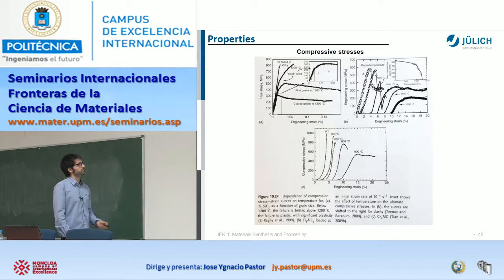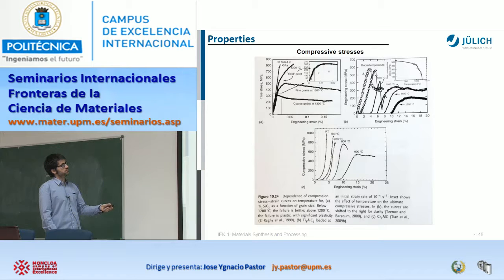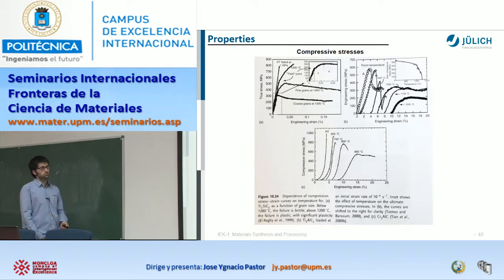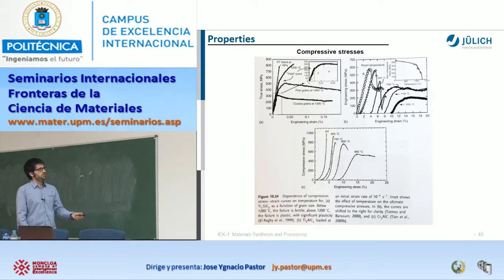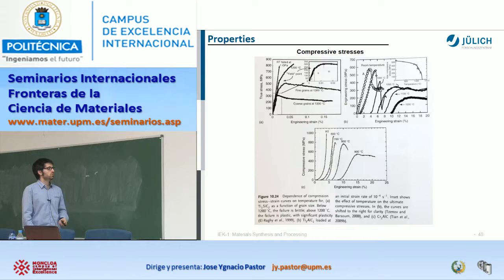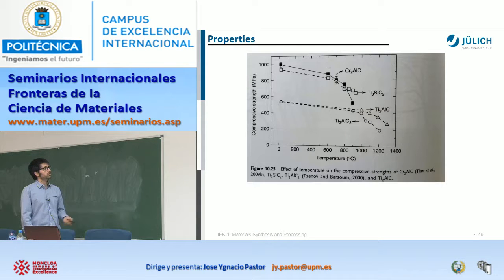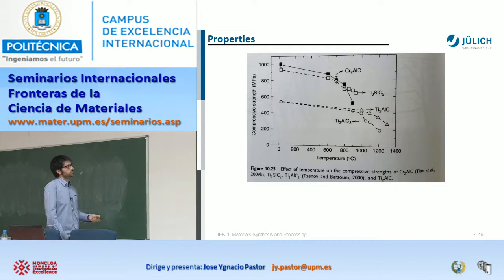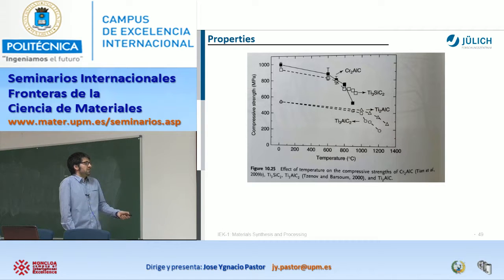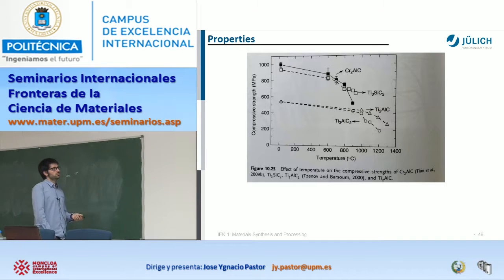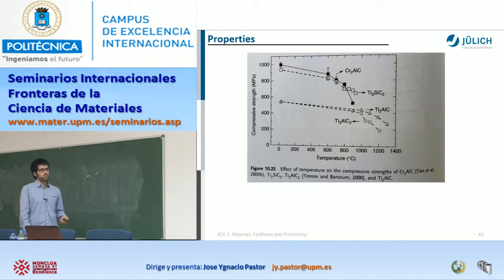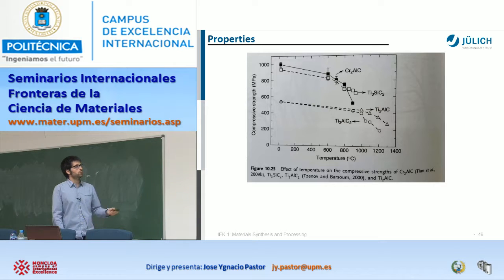And also the compressive stress, how they react here. It's not a catastrophic failure. It goes better, or also at higher temperature they start to develop ductile mechanisms that are much better than even at room temperature. I think it's quite amazing. More work has been done at high temperature, but it's quite important. Here, about the compressive stress, for example, of this chromium phase, about the effect of temperature. We are talking here about this intermediate temperature, and they keep already good values. For example, ultra high temperature ceramics, I think they keep at this temperature even better values, but other properties are much lower than these MAX phases, which present really good values.